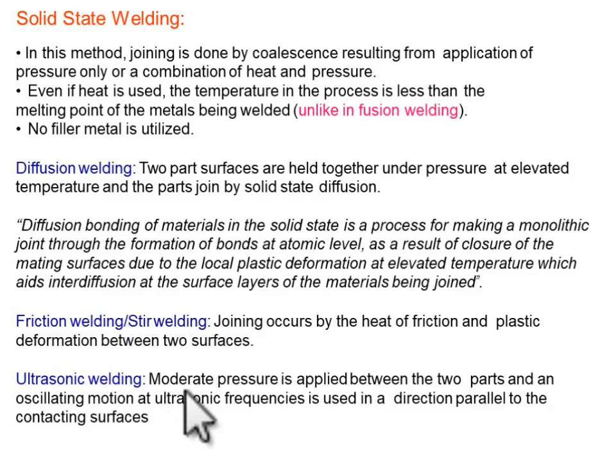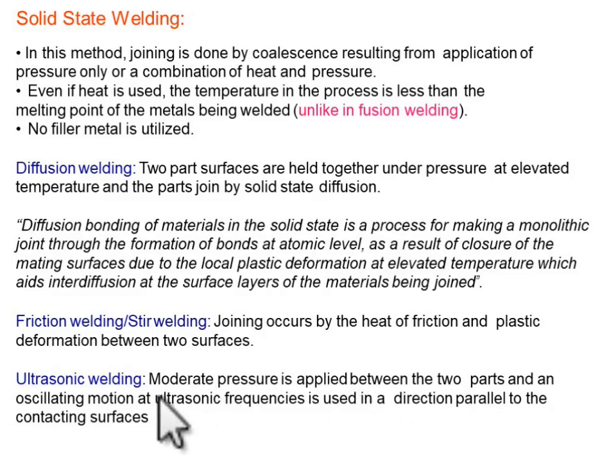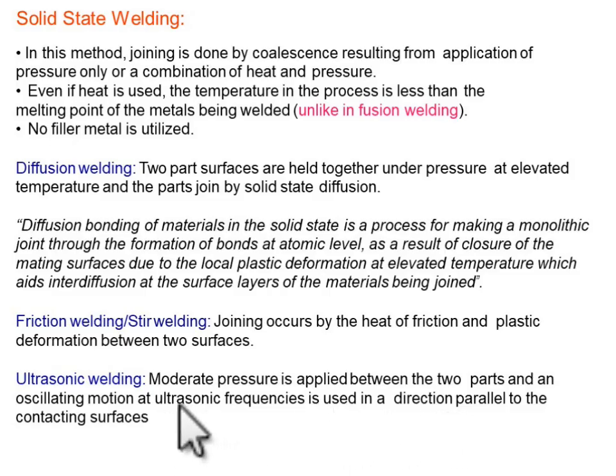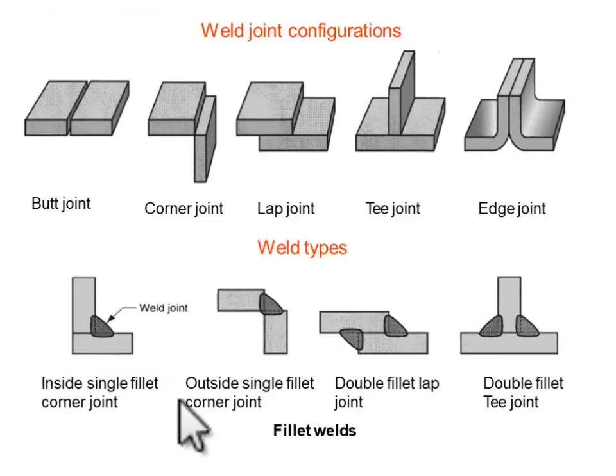In ultrasonic welding, we provide moderate pressure between the surfaces and oscillating motion at ultrasonic frequencies is used in the direction parallel to the contact surface. Due to this, the temperature increases and the joining process is completed.